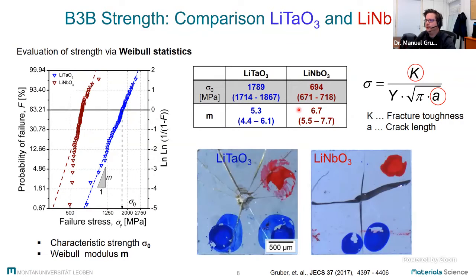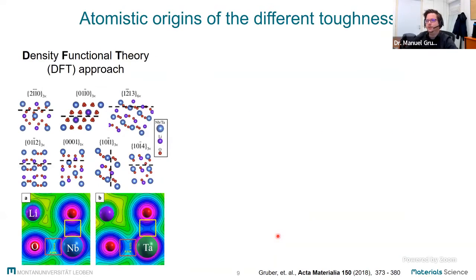At first, we had a look onto the fractured specimens, and we could see that every specimen for lithium tantalate fractured somehow like this, and every specimen for lithium niobate somehow like this. So we were pretty sure that cleavage planes seem to dominate the fracture behavior in those materials. So we went to some colleagues that are able to do atomistic modeling, and they had to look onto certain planes of families of planes, and had to look onto the bonding forces between the atoms and calculated work of separation, and out of this, the toughness of different planes.